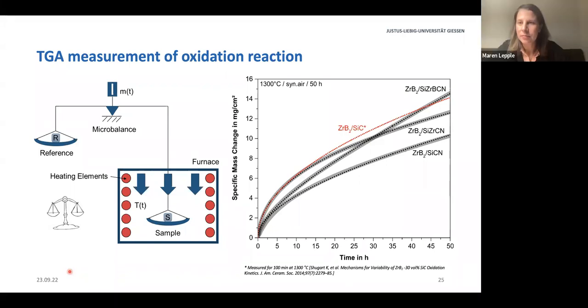It's a pellet. And I think we have several things going on. We do not only have the parabolic oxidation, but we also have linear mass loss because, for example, the boria, which should be liquid, also evaporates at these temperatures slowly. And there are also other oxidation reactions going on, which have some linear portions. We actually calculated the kinetics, and we found different linear portions to it, but it was really difficult to derive which reaction accounts to which kinetic. So basically, there are many reactions taking place.